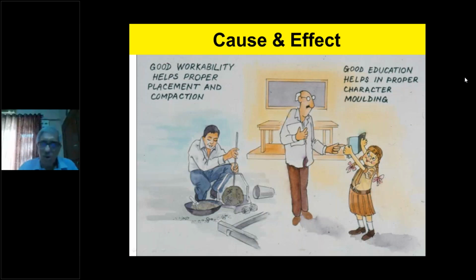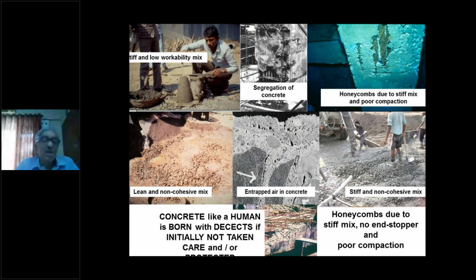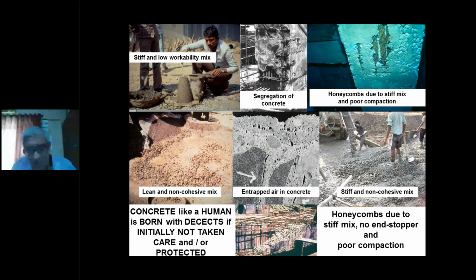Good education helps in proper character molding. Good workability helps proper placement and compaction. So both human being and concrete behave quite identically when young or in plastic stage. Concrete, like a human, is born with defects if initially not taken care of or protected. Honeycombs due to stiff mix, no end stoppers, and poor compaction build the defects, and these defects remain forever in concrete. And defective concrete, even if it is repaired, is not as good as the concrete made in a correct manner without the defects.